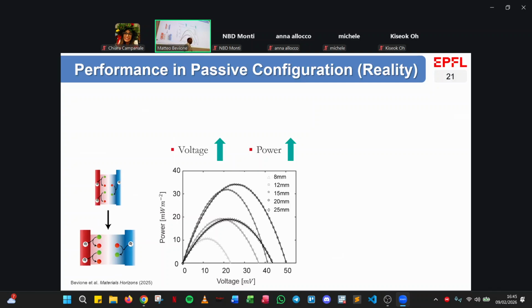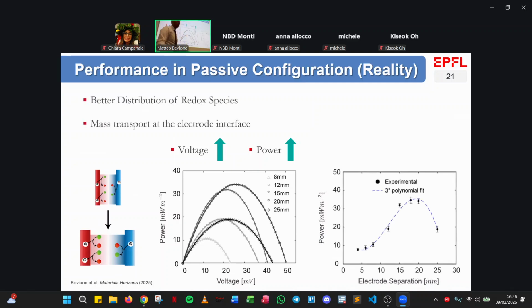So initially, yes, if you thicken the cell, you get a better power output because of the temperature gradient. But if you stretch this too far, then you will get a decrease in the power. And why so? This is particularly evident if we report the maximum power with respect to the electrode separation. So here you can see that there is a plateau at first and then a sudden decrease.